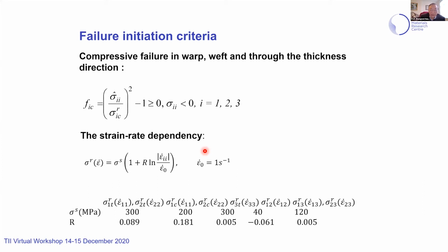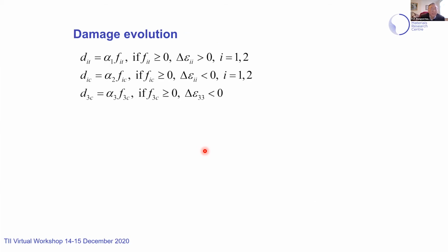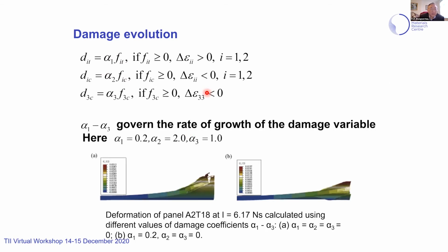These are some material parameters we use for the quasi-static strengths and also R, this coefficient. Then there is damage evolution. We have the damage failure criteria, and we also introduce alpha 1 to 3. In our modeling, we use alpha 1 equal to 0.2, alpha 2 equal to 2, and alpha 3 equal to 1. But we also did a test using all alpha 1 to 3 equal to 0, and we get this kind of blast failure mode. If we use alpha 1 equal to 0.2 but alpha 2 and alpha 3 equal to 0, we get this failure mode, which is much closer to the real blast failure mode.